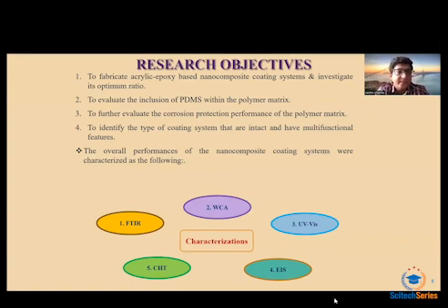It has this feature where it enhances the hydrophobicity of the coatings. Then we also want to further evaluate the corrosion protection performance of the fabricated polymer matrix. We also need to identify whether our multifunctional coating system is intact, and whether there are any cracks, as we know that cracks lead to lower corrosion protection performance.